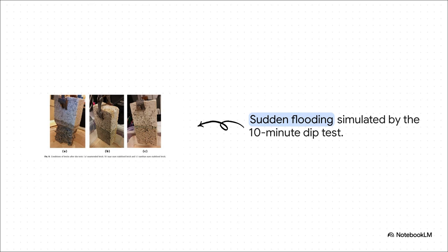It doesn't just simulate rain, it simulates sudden, severe flooding by completely immersing the bottom of the bricks in water for 10 straight minutes, while they're suspended in midair. The unamended earth essentially just visually deteriorates, falling apart right into the water bath. But the guar and xanthan gum samples, they remain remarkably intact. They maintain their sharp edges and structural shape despite the sudden total immersion.